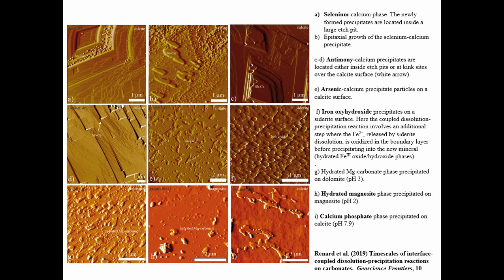So we've looked at a lot of toxic elements because a lot of our work is looking at how can we sequester, how can we, from solution, toxic elements. So this is a lot of work that I've done together with François Renard, who's now in Oslo. You can see here we've looked at selenium, which I showed you the images of. We've looked at antimony and arsenic and various other surfaces. The main thing to see here, together with dissolution, we're getting the formation of nanoparticles in specific places on the surface. Those specific places are where dissolution is fastest.